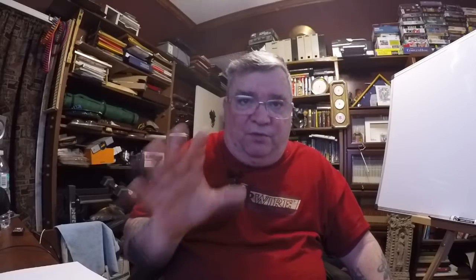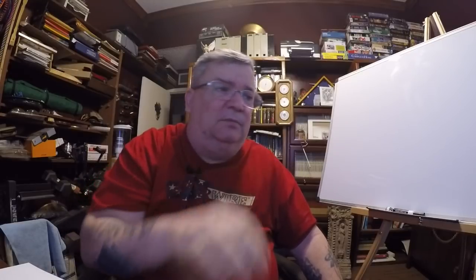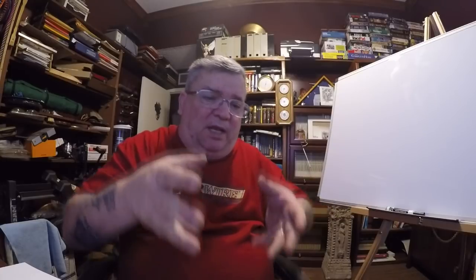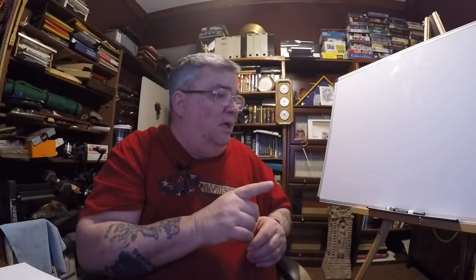Alright, and that much I've covered. There's nothing on that side. You apply the tin to the surface of the bearing shell where the Babbitt is to bond with the shell. Okay. And I showed it with the tin stick, and I showed it with the tin bath. Now, once you've tinned it, you're going to put on those gaskets, and once you have the gaskets glued into place, that'll hold it in place, because while you're trying to get the bearing and setting it onto the mandrel. Now here's what the mandrel looks like.